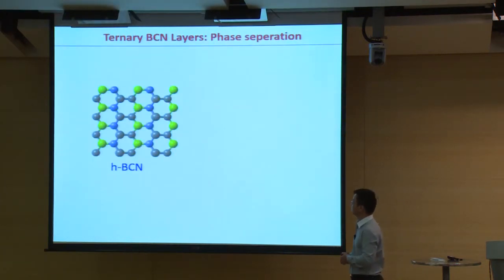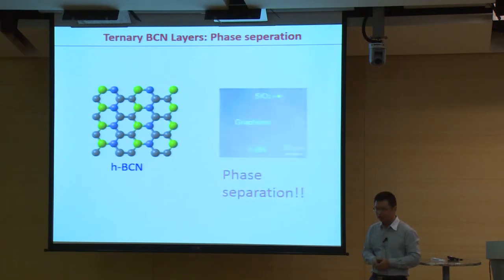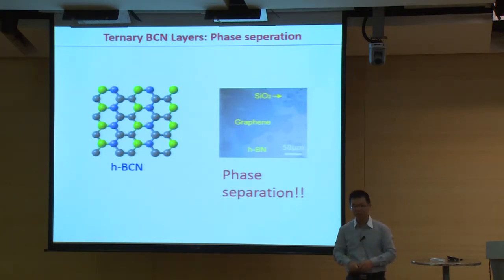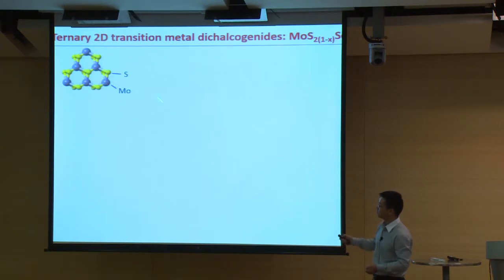And okay. As we previously discussed, the BCN thin film is a ternary system, but unfortunately, for most of the cases, they won't become a homogeneous ternary system. Instead, they will get some domains, boron nitride domains and graphene domains, because of the phase separation. But the TMD families give us another playground for the ternary system, and possibly we can get a truly homogeneous ternary system. So here we have a moly disulfide.